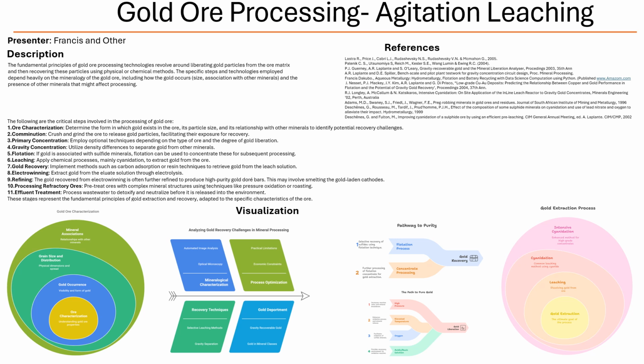And CIL? CIL can be advantageous if the ore leaches quickly, but it typically requires a higher carbon inventory. You need more carbon in the circuit. And what about CIC? CIC is often used for smaller operations or for treating solutions that are already pretty high in gold concentration. So it's like a specialized tool for specific situations.